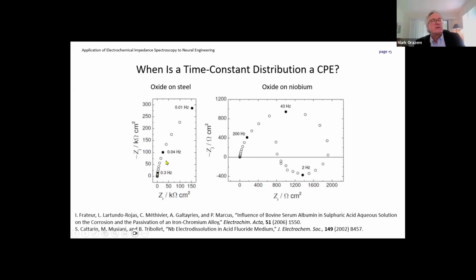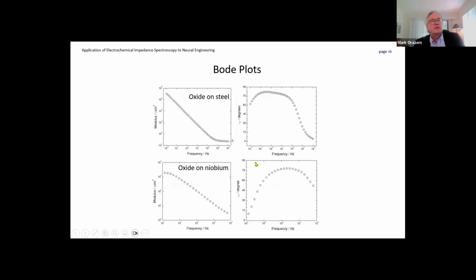The high frequency behavior looks very similar in a Nyquist plot for the oxide on steel as it does for the oxide on niobium. And the situation is not improved if we look at Bode plots. If we look at Bode plots, let me focus on the phase angle. Then at high frequency, what we're seeing is that the phase angle wants to tend towards zero. And the reason for this is that the interfacial impedance becomes very small, and what we're really seeing in the impedance is the ohmic resistance.